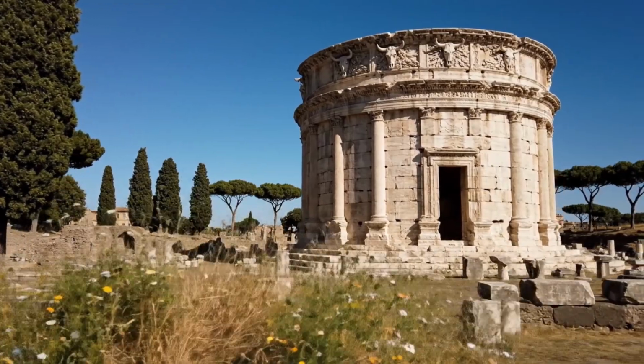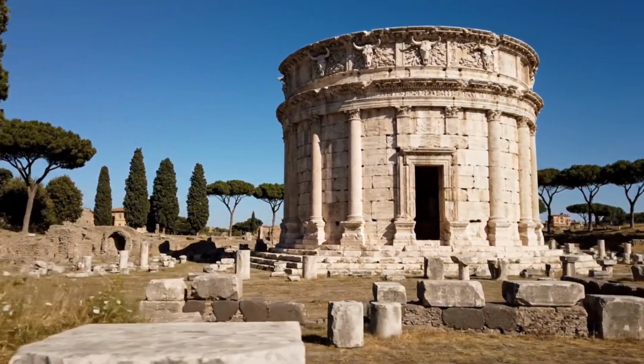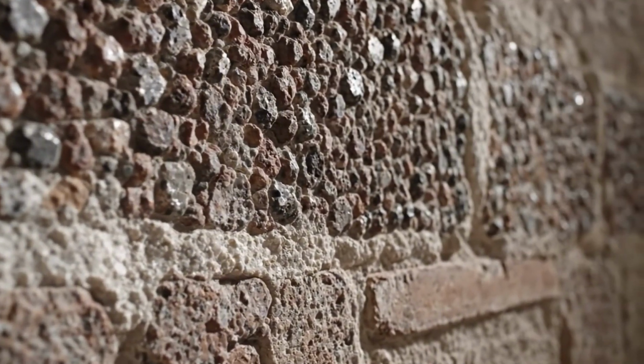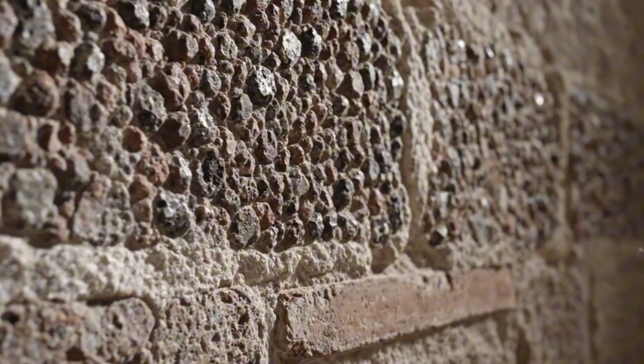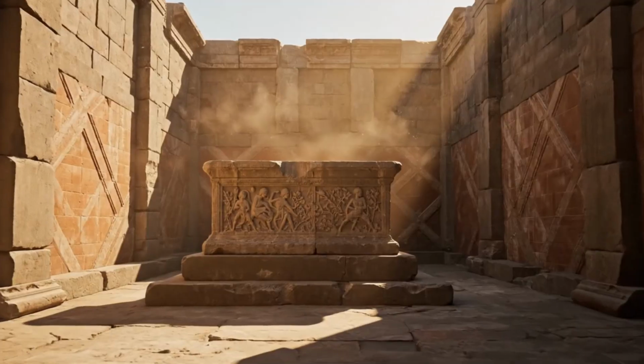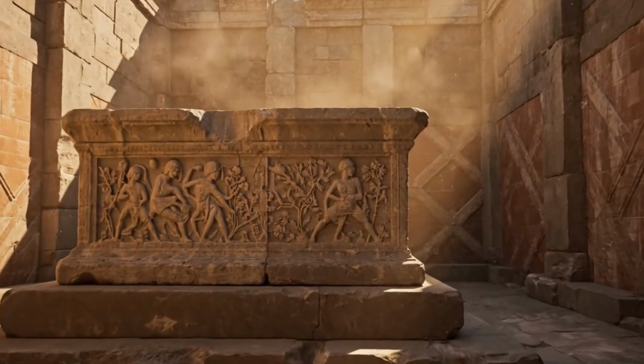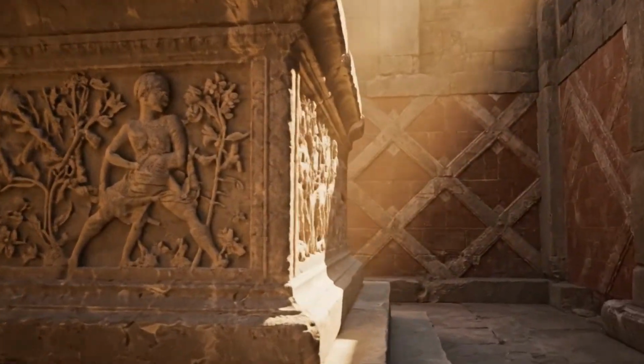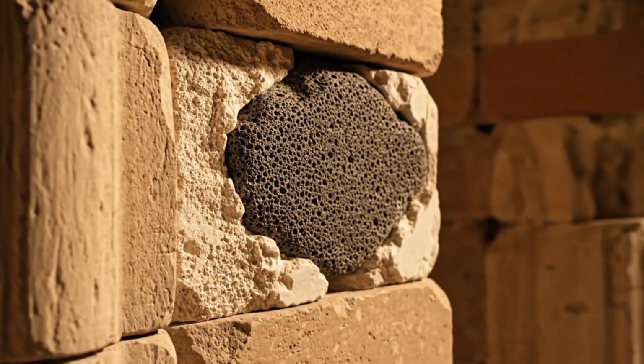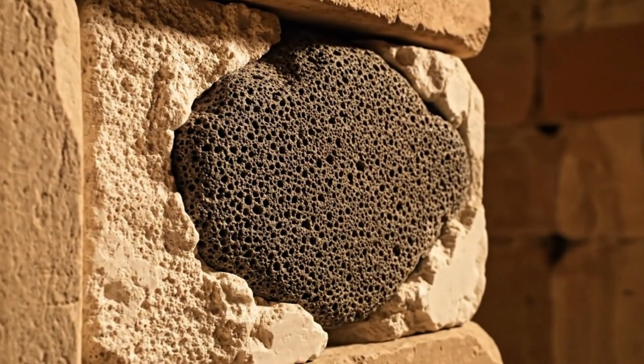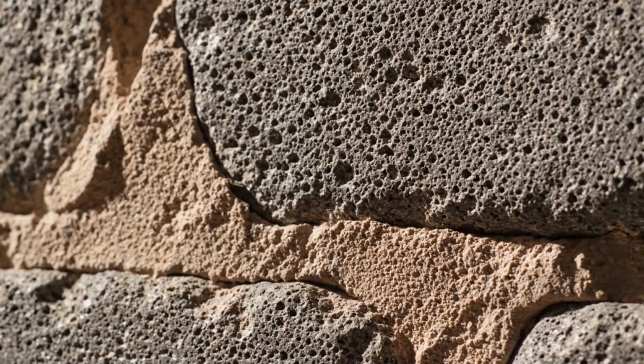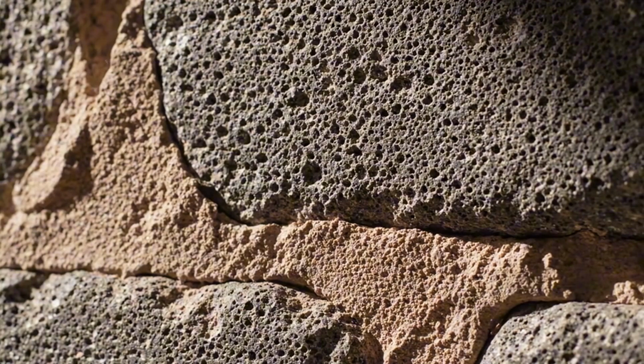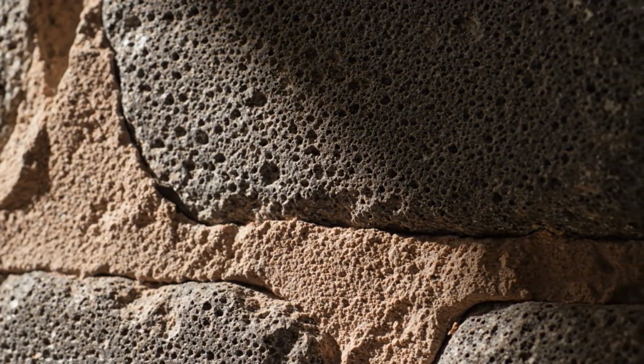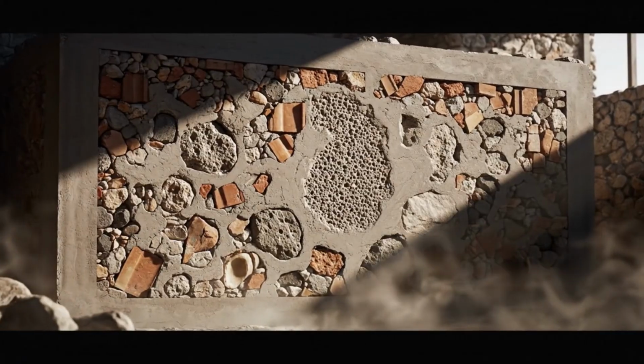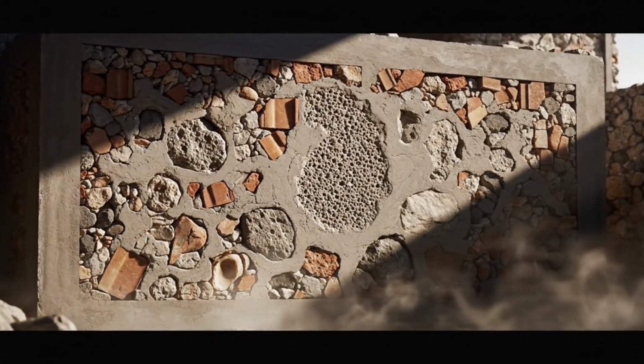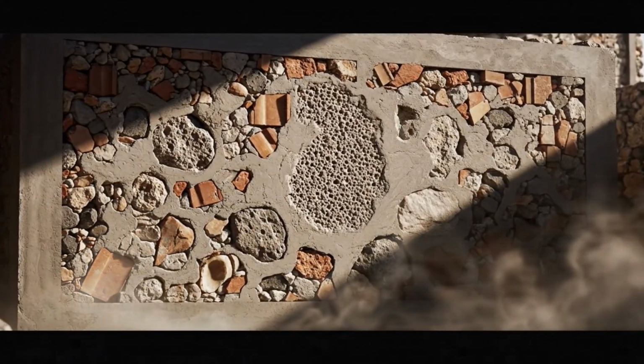These results support a striking conclusion. Roman concrete was not merely resistant to damage, it possessed an intrinsic capacity to respond to damage. The integration of quicklime through hot mixing created a distributed network of reactive inclusions that could activate when needed. In modern materials science, such behavior is described as self-healing. In the context of Roman engineering, it reflects a practical understanding that materials exposed to time and environment must be capable of adaptation. Seen in this light, the lime clasts are no longer imperfections. They are evidence of intentional design.